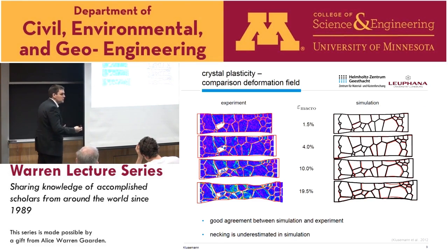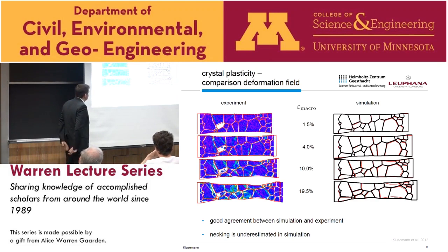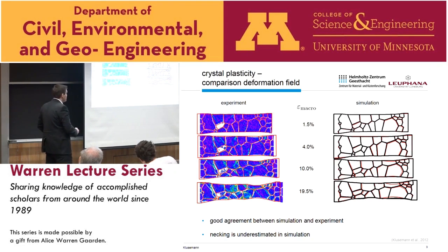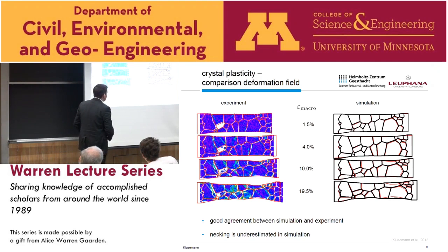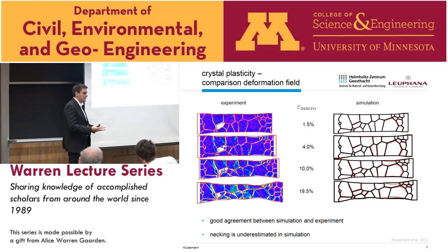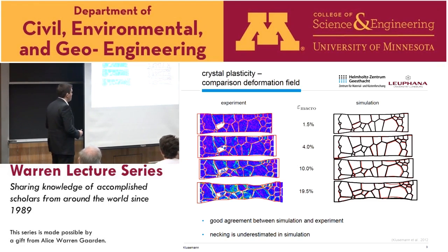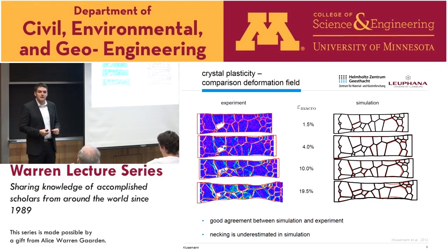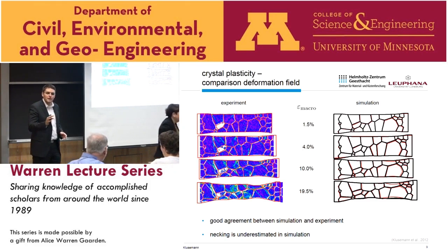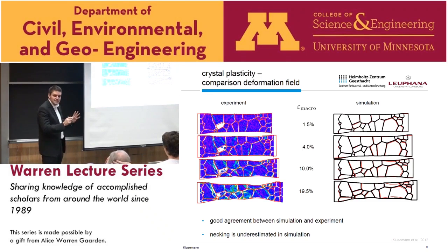Okay, so we went a step further. We included now the hardening which we identified on material data from the literature. And what we could see is, first of all, we get a very good agreement until 10%. It's very excellent in this sense. And also to 20%, we see at least the correct tendencies. However, we underestimated the necking phenomena in the simulation compared to the experiment. So there's no calibration here. Sorry, there's only calibration regarding the material properties. Yeah, the material properties have to be identified. There's no further calibration on the model, no.